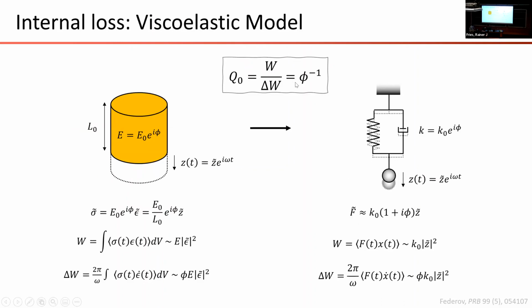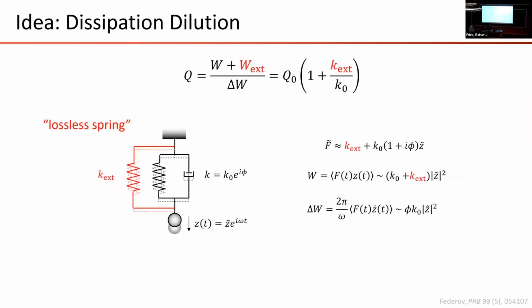Okay. So I just want to introduce that notation, because if you believe this Zener model on the right, it's very easy to think about how to engineer an effect called dissipation dilution. In abstract, what I'd like to do is superimpose onto this mass-spring system a lossless spring. How I do that, it's not clear. But if I could superimpose in parallel onto this mass-spring system a lossless spring with no retardation, then I could increase the stored energy without changing the loss. So that's the idea here. I want to take this elastic body and somehow embed it into a conservative force field that increases the energy without increasing the loss.